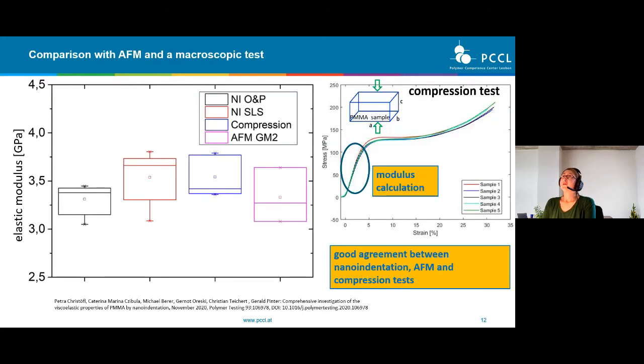So now, if we compare those nanoindentation data with AFM nanoindentation and with macroscopic tests, we get these results. But first of all, I would like to show you the compression test on the right side, where we used 5 samples of PMMA, and we got from this compression test, which is a common macroscopic test, a stress strain curve, and calculated the modulus from the slope at the beginning of the curve.